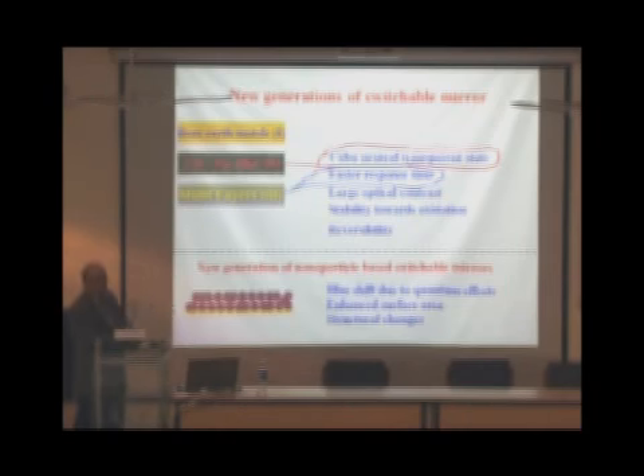So because of these two effects, we thought we would make rare earth nanoparticles, which is very difficult to form because of a third reason. They form oxide. Most of the chemical methods cannot be used for making nanoparticles of rare earth materials. So we started working on this.